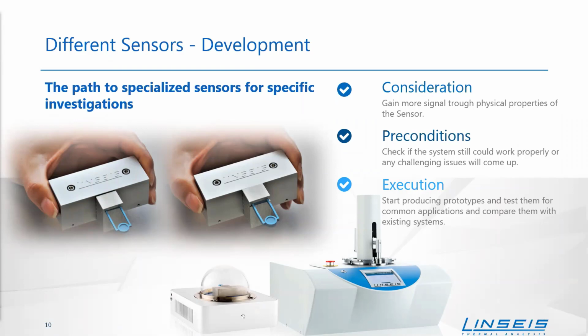Now we should have a look at the convection. As you know, especially above 400 degrees Celsius, convection is pretty important for DSC, and so we should have a look if we change the size of the sensor in the height, are there any problems we could receive? I can say no, because the sides of the sample side and the reference side in comparison to the height of the sensor are much bigger, so we won't receive a problem here theoretically. But later we should have another look at this in the hands-on, so we will see on the measurement signal if it works or not.